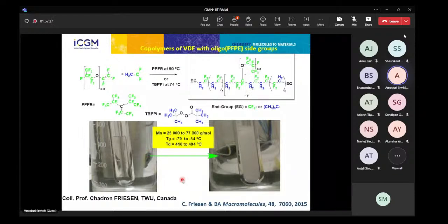So we had molecular weights ranging between 25 to 77,000 grams per mole, with a Tg ranging between -79 to -54, which was exceptional. I have to say, don't forget that the Tg of PVDF is -40. And by adding some side groups, usually you increase the Tg, but because of the presence of very low Tg, which is about -100, -120, it was possible to have very, very low molecular weight with a very high thermostability. Because you can say, okay, you make low molecular weight, but if we make low molecular weight, we couldn't get so high thermostability because you have some evaporation usually when you heat it up. But even up to about 500 degrees Celsius under air, this was exceptional.